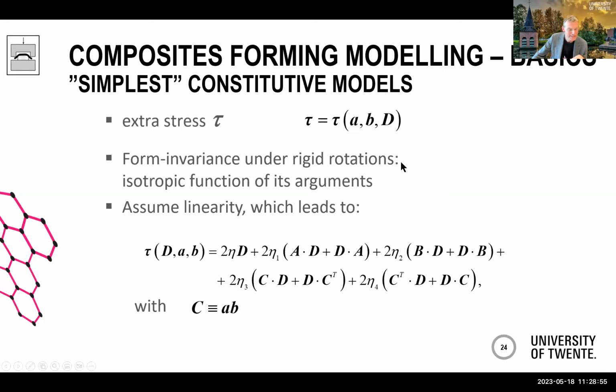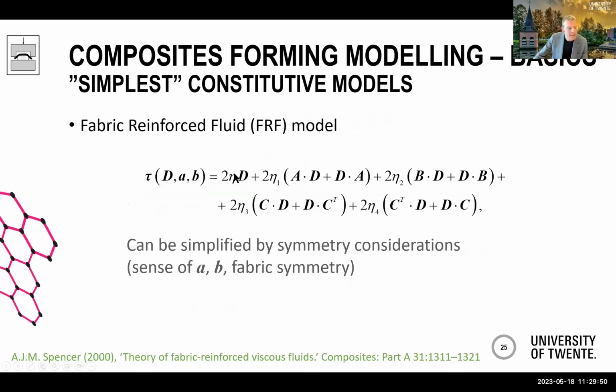Well, if you then go through the classical continuum mechanics engine, more or less, imposing form invariance under rigid rotations, then such a function should be an isotropic function of its arguments. And if you then assume linearity, then you end up with something like this as a general, but I would say the most simple way to describe the extra stress as a function of its arguments, the deformation rate, and the fiber orientation vectors, which can be written as these fiber orientation tensors, adding this dyadic product C over here. So from this we've got 1, 2, 3, 4, 5 viscosities which need to be characterized. I'd like to have it a bit simpler, but nevertheless, this is a well-accepted formulation introduced by Spencer, published in 2000 already,